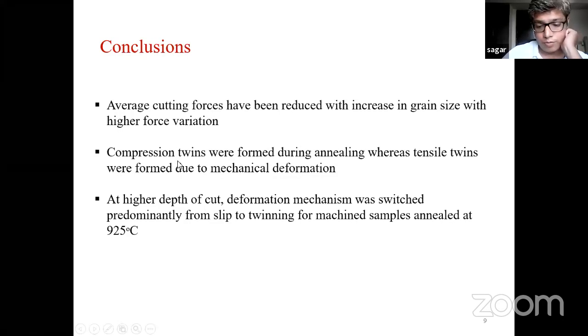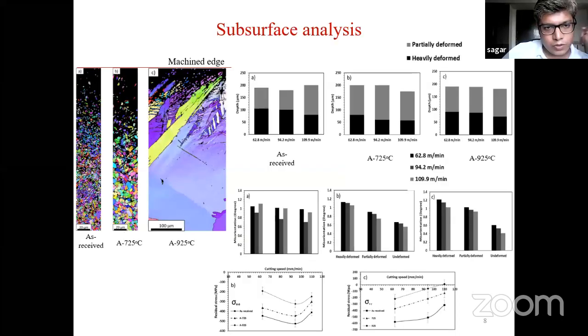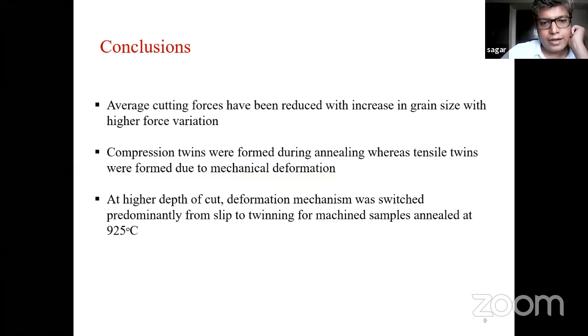The compression twins were formed. So here in this region, if you see, these are nothing but the twin formations. That means the grain orientation has been mirror image to each other. Between this grain and this grain, there are almost mirror images at some angle. Those are nothing but the twin formations. For the highest annealed sample, the deformation mechanism was switched from slip to twinning. Slip phenomenon is when the dislocation movement happens inside the grain. Twin phenomenon is the one which I just told you. So both have contributed to the plastic deformation.